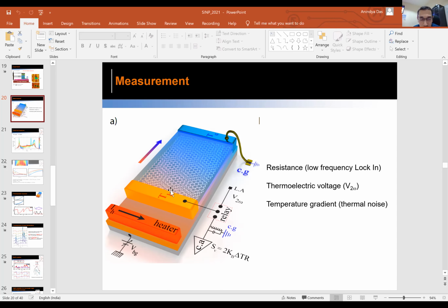Because this contact is of the order of kilo-ohm. Now imagine that we are making this 1D contact, because we etched it and it is a 1D contact. So basically the contact is like an interface, just like a single line. Now, thermoelectric voltage is proportional to the temperature difference, right? So what I'm trying to say is that within such a small length scale, a few angstrom, where the contact is coming, the temperature difference is almost close to nothing. There is no temperature difference across it.